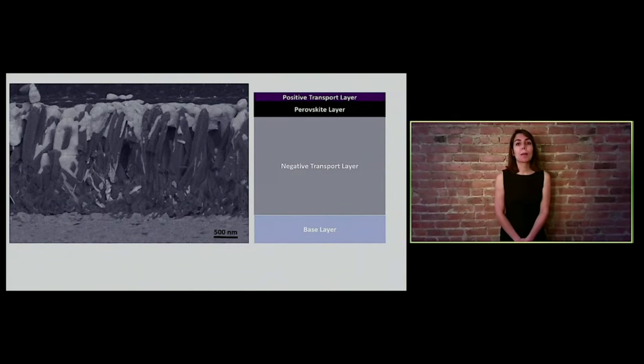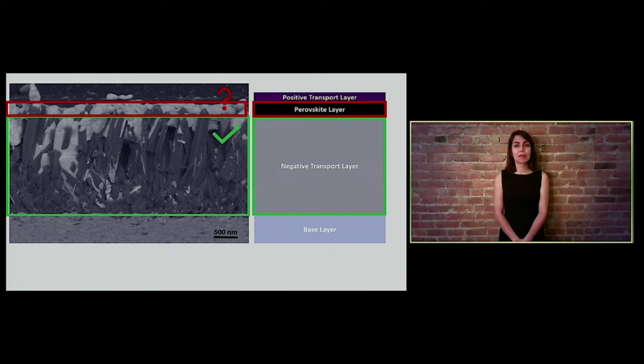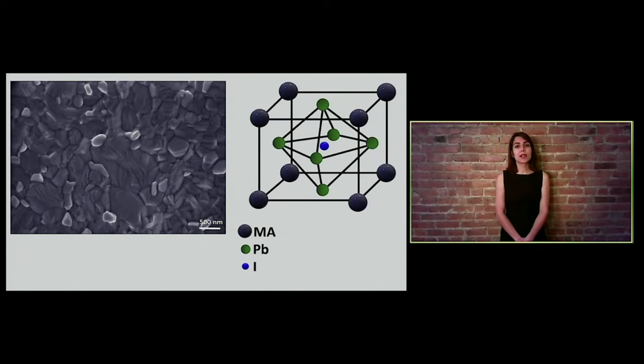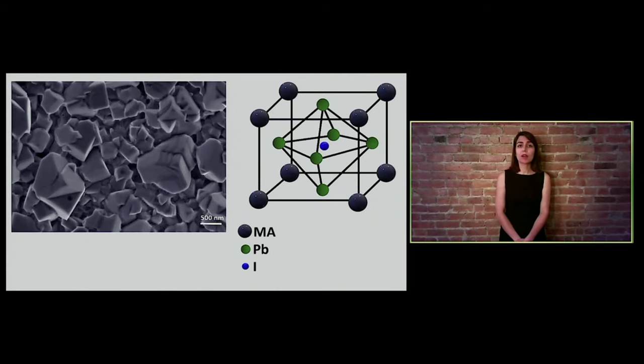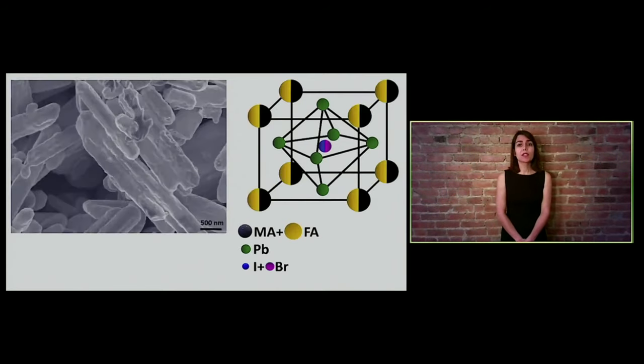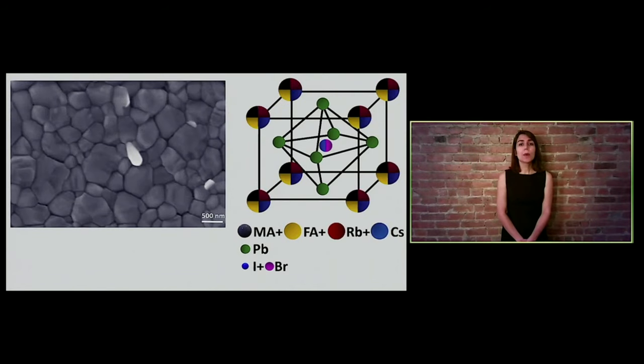So far, I've been telling you about my efforts with regards to optimizing the negative transport layer. Now let me show you what I've been doing about the perovskite layer. When it comes to this layer, I'm interested in how I can fix the composition but vary the deposition method, or fix the deposition method but vary the composition, to possibly tailor and fine tune the properties of the resulting perovskite solar cell. And what we discovered was that the composition that you're looking at right now has superior properties in terms of both efficiency and stability over every other composition that we have tried so far.